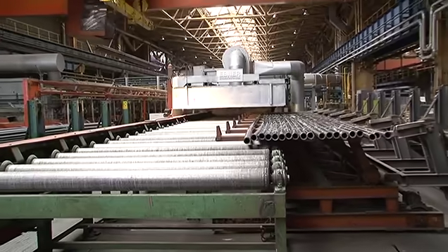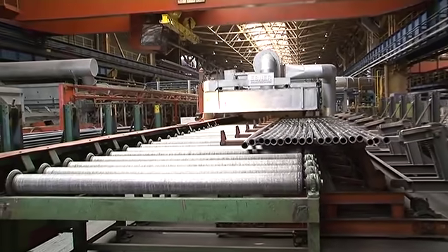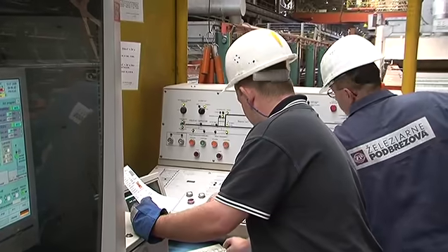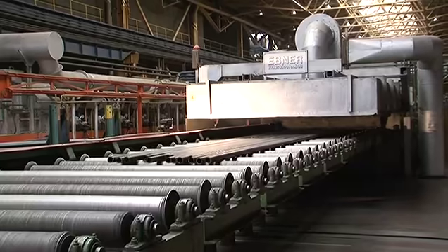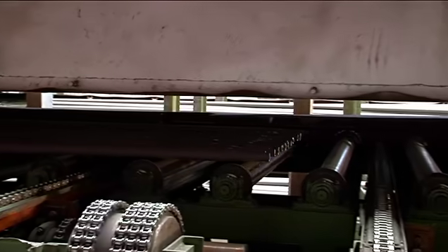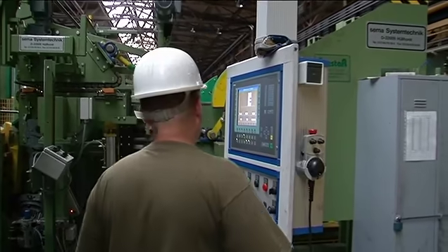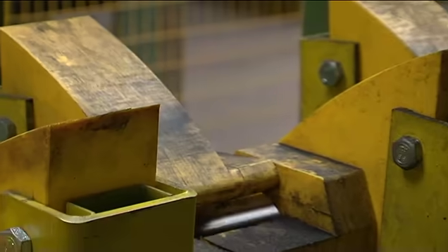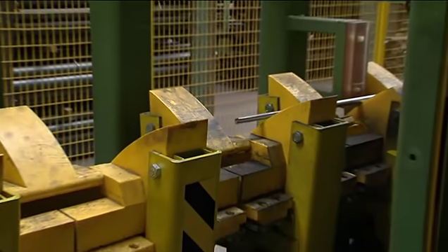Under such high loads, deformation of the crystalline lattice occurs in the material, as the tubes become less rigid and fragile. To restore the required mechanical properties, annealing in the continuous annealing furnace in a protective atmosphere is required. After heat treatment follows either another processing cycle or finalisation.